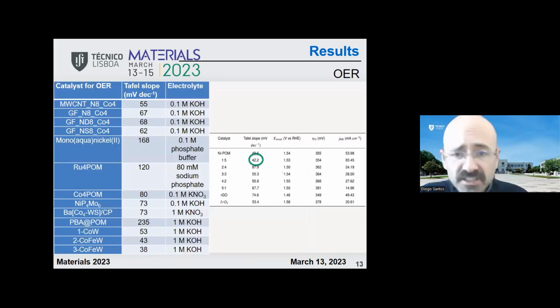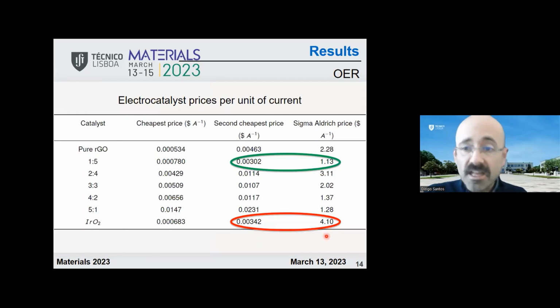So here we have a comparison of the different materials and the Tafel slopes that I was showing, and this also compares with the literature that was found with similar materials. So our results were very promising for oxygen evolution reaction. Moreover, if we consider the price of the catalyst per unit of current, considering the higher currents that we have managed to produce with this composite, the cost of the material per unit current was lower than the one from iridium oxide. So these were very interesting results.